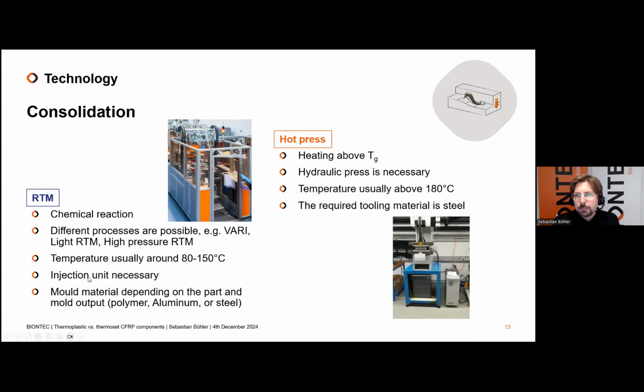And of course, in every RTM process, but I think you're familiar with that, the injection unit is necessary. The preferred material for the mold depends on the part and the surface quality of the part, and of course on the mold output and how long and how many parts we have to produce per year. If we start in the engineering or development phase, often we use a polymer mold. For prototypes or start of production, we often use an aluminum tool, and later on, if we go to higher volumes, then often we transfer this to a steel mold. But an aluminum mold is also capable of more than 2,000 parts a year. So aluminum also has its advantages.